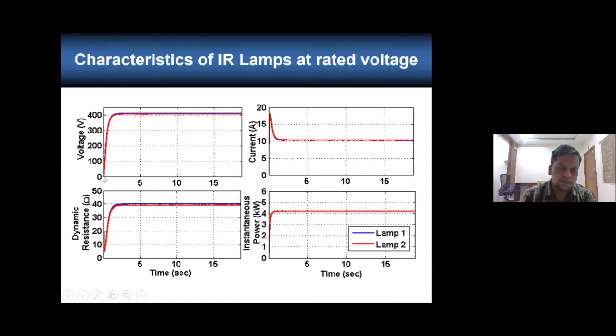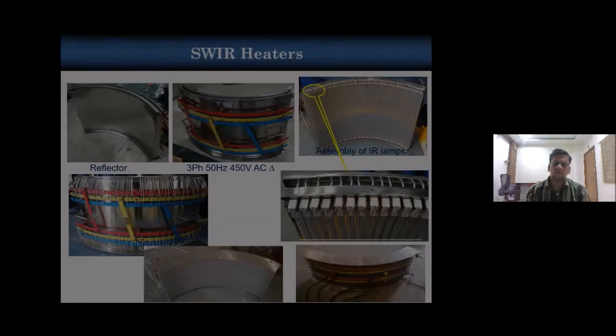Now this graph shows the characteristics of IR lamps when I give the full rated voltage. You can see I have given a voltage of 415 volts to a 4 kilowatt lamp only. Current initially surges to almost 17-18 amps and settles at 10 amps. This initial part is due to surging, mainly because of the cold resistance of the tungsten filament. Then we can calculate dynamic resistance. Within fractions of seconds it can reach its rated power of 4 kilowatt at 415 volts, at a very fast rate. That is the advantage of the IR heater.